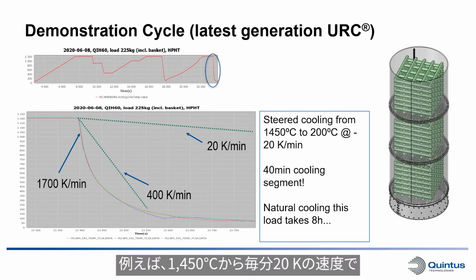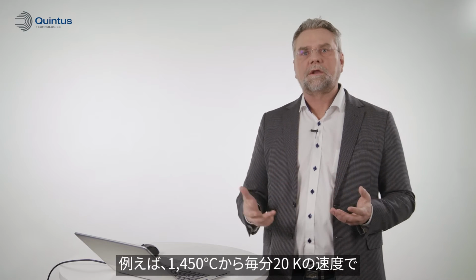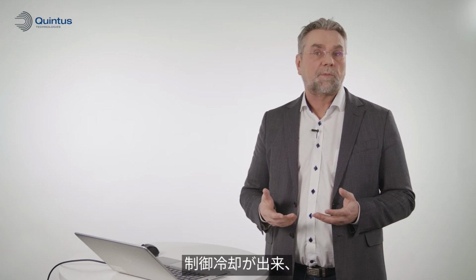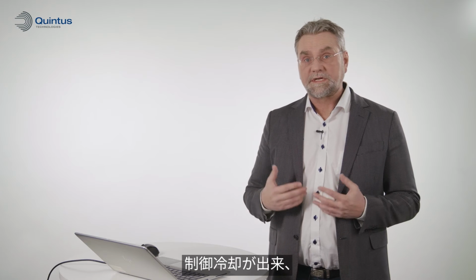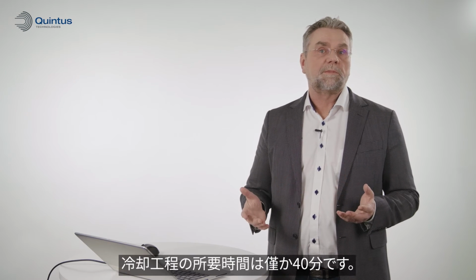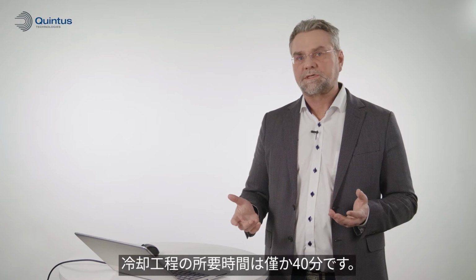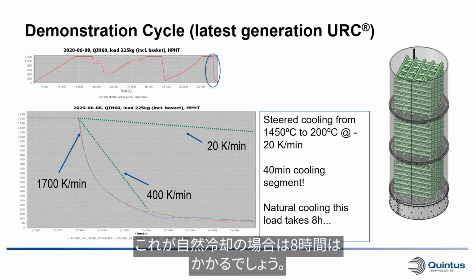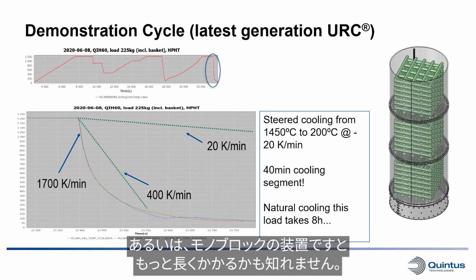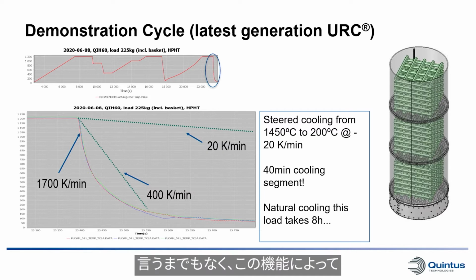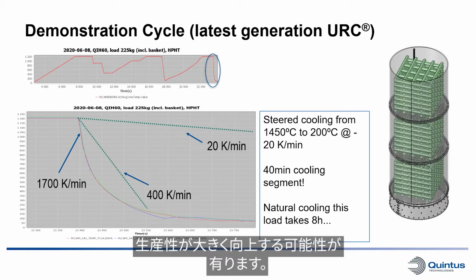As an example, if we did a controlled steered cooling at 20K per minute from 1450 degrees centigrade, the cooling segment would be only 40 minutes long. A natural cooling of a load like this could take 8 hours, or even longer if you have a monoblock system. So of course, there's a lot of potential for productivity increase using this functionality.